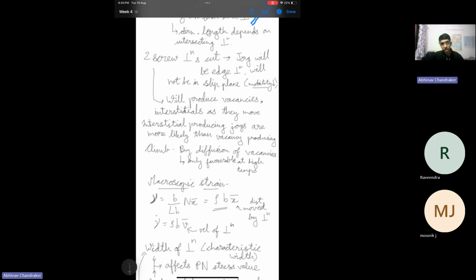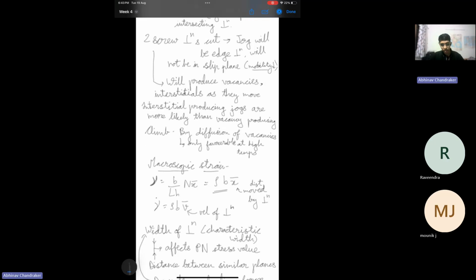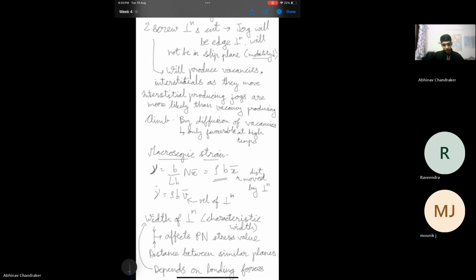So two screw dislocations cutting each other will lead to an immobile jog, and that will drastically reduce the mobility of the entire dislocation since a portion of it cannot move. It's like trapping a dislocation by fixing one portion of it. And the movement of this portion can lead to production of vacancies and interstitials. Also, sir had mentioned that interstitial producing jogs are more likely than vacancy producing jogs.